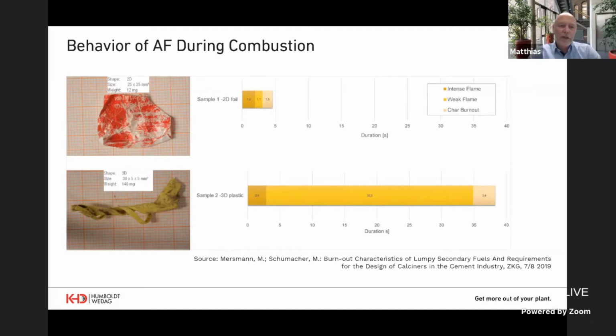And what you see here is the result of an investigation that I've done already 2 years ago, where we looked at the different combustion behavior of typical representatives of a mix of alternative fuels. On the left-hand side, you see a very thin foil of plastics. And here you see even still very small particle of higher density plastic. And what you see here is the duration it takes for these samples to ignite and burn out.